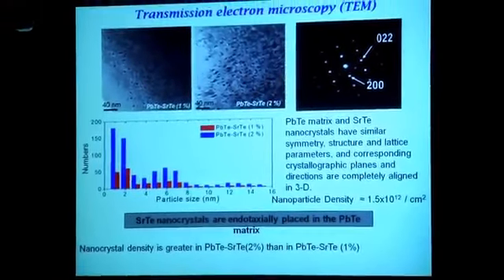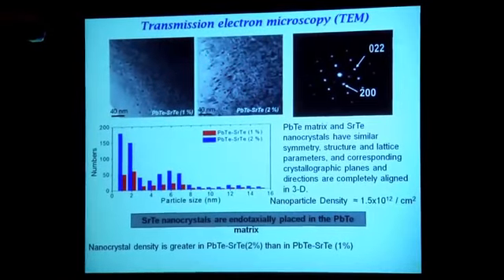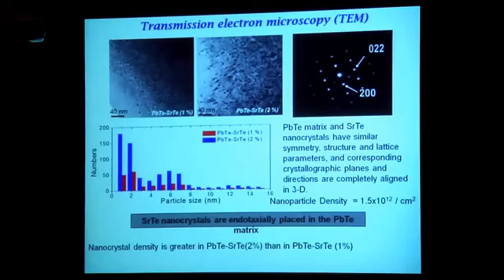Another remarkable thing here is, even though this looks like a messed up picture, with these nanodots all over the place, if you take an electron diffraction pattern from these areas, you see a single crystal. These are aligned endotaxially. These are single crystallites of strontium telluride having precipitated in lead telluride, and they're endotaxially aligned, all of them in the same direction. So you get no splitting. This is a single crystal. The density of this we estimate about 10 to the 12.